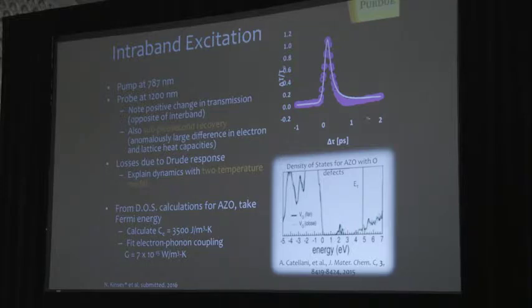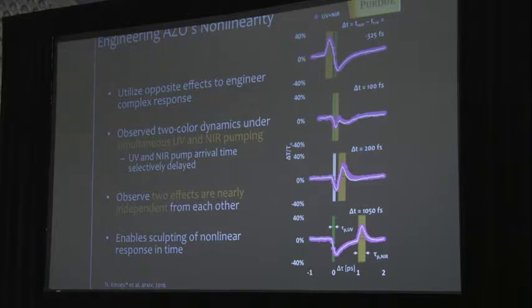And we were able to fit the experimental observation very well with the theory, for which we used a calculation of the density of states, and so we calculated the electronic heat capacity and extracted the electron-lattice coupling. And here's the possibility to engineer nonlinear response. That's really kind of interesting. First of all, with the blue line here, I'm showing when we have both pumps, UV pump and near infrared pump, and with this purple, I'm colorblind, I believe it's purple, it's the result of doing the two pumps independently, either only 800 or only 325. And you see that the simple algebraic sum fits very well to the case when you have two pumps, which means that these two contributions work independently. If you're interested why, I could suggest our qualitative explanation.